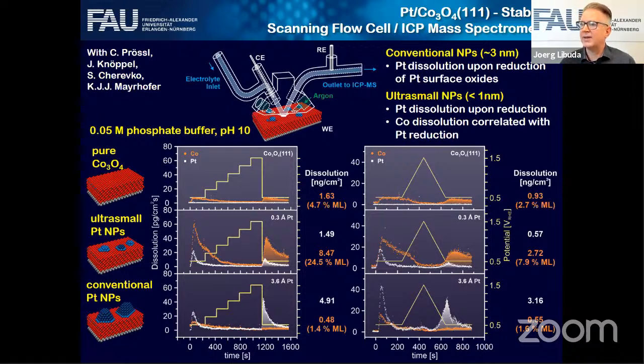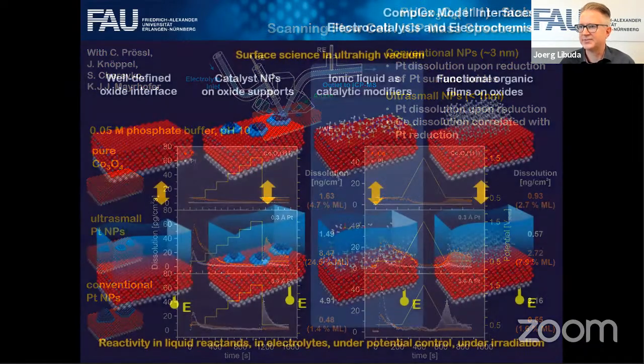So what is happening here is we believe that you actually have this exchange process where platinum is embedded into the oxide support, cobalt is ejected, and this ejected cobalt is then easily dissolved in this experiment. So this is our potential explanation.